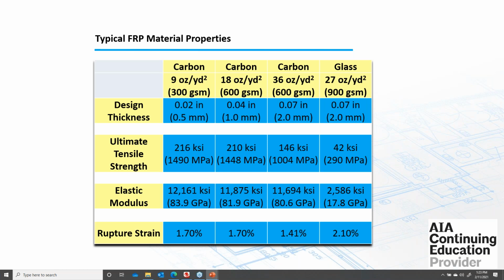But when you look at the strengths that we're seeing, the tensile strength is around 1,500 megapascals, around 210 or so kips per square inch for most of the carbons, and the glass, again, has less strength than the carbon, but still pretty good, considering it's only 0.07 inches or 2 millimeters thick. The stiffness is really the governing property. However, everybody reports the tensile strength. It's part of the ASTM 3039 reporting requirements, but the tensile strength is really irrelevant when we're designing. All of the design codes, be it the ACI or the CSA design guidelines, everything's based off of stiffness, and we'll see why that is a little bit later here. But the stiffness is very, very good, obviously, for all the products. And you can see those rupture strains down there as well, which have a big part in the design of these systems.